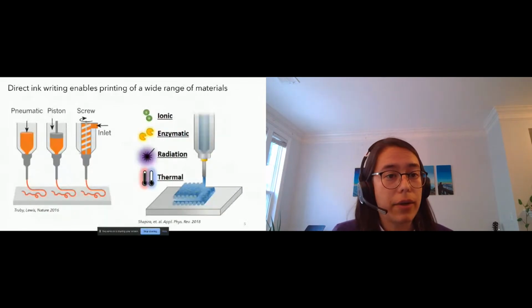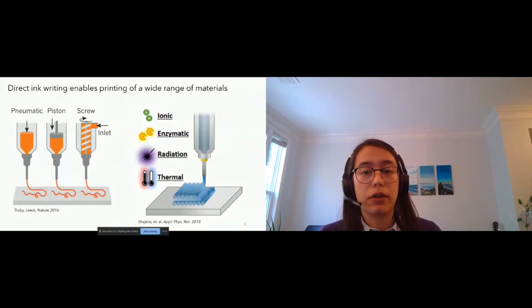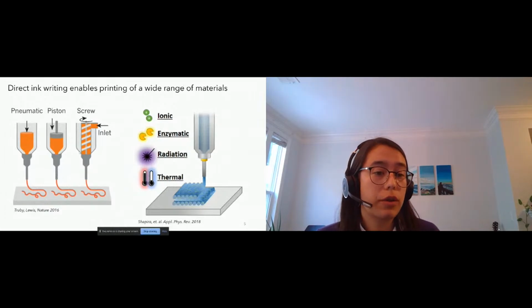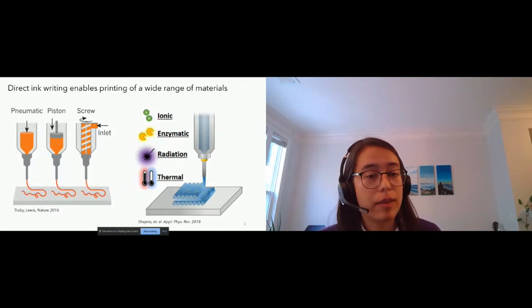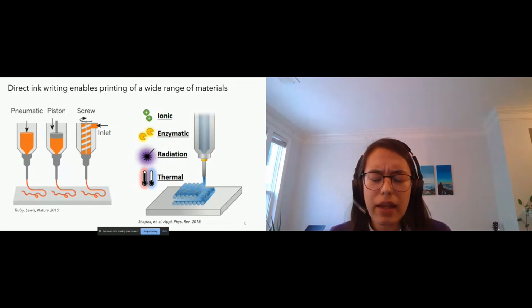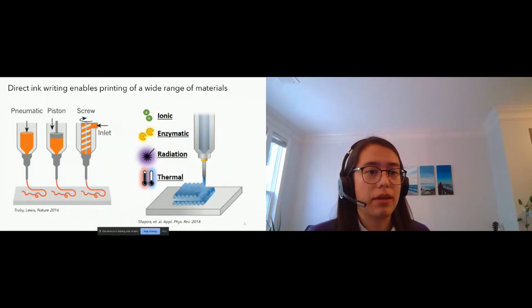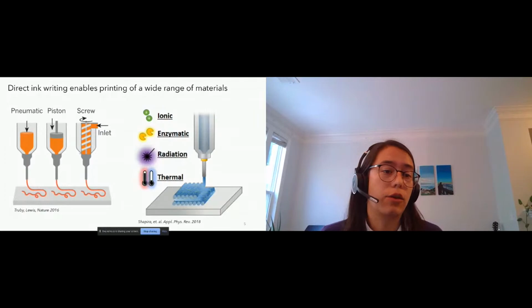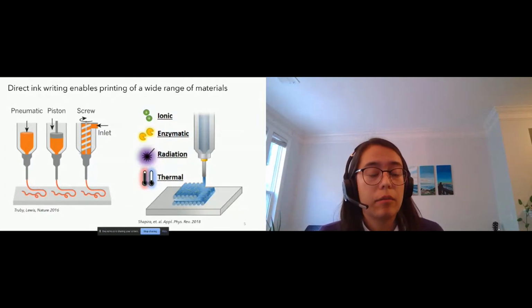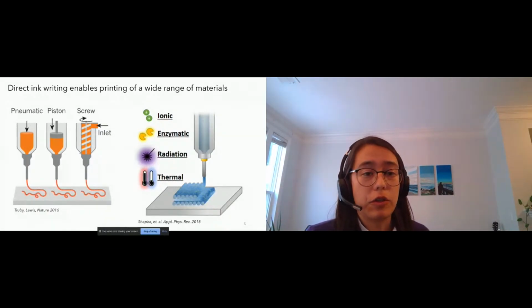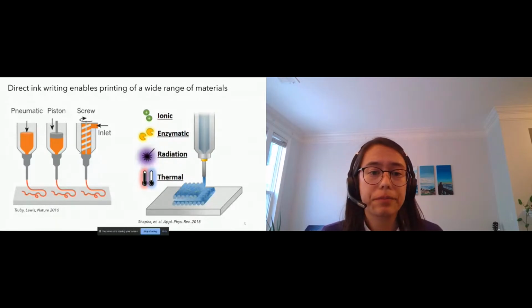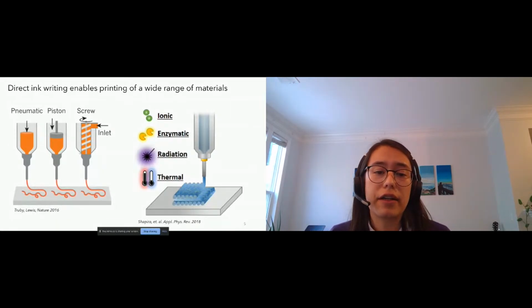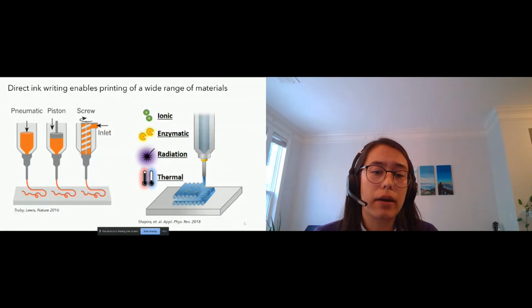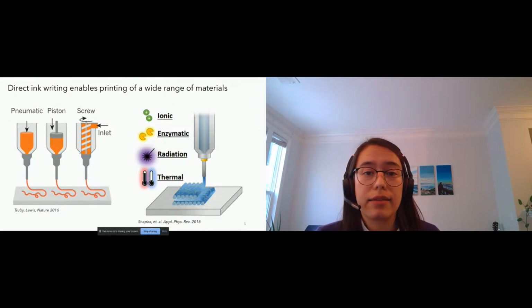The way that direct ink writing works is you have a reservoir that's full of your ink, and you extrude it through a nozzle and write out continuous filaments onto a substrate. You can use a variety of extrusion methods. You could use pneumatic extrusion, so you have an air pressure that is pushing this fluid out of the nozzle. You could use a piston, you could use a screw. And then there are a variety of curing techniques. Once your part is written out onto the substrate, you can cure it using a variety of techniques.